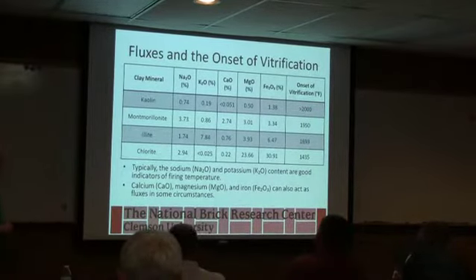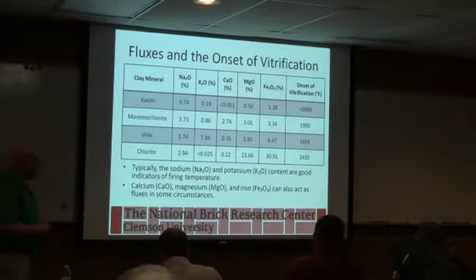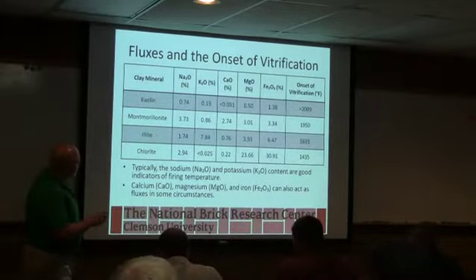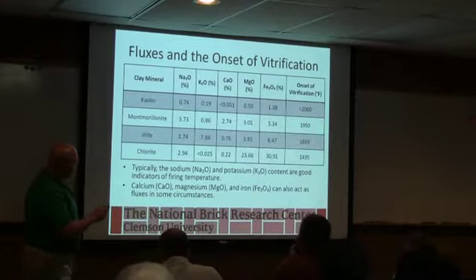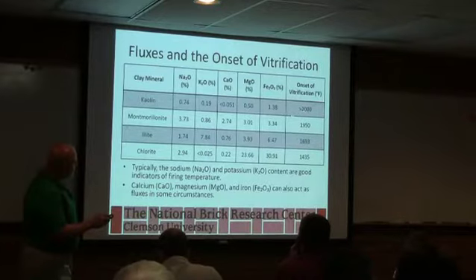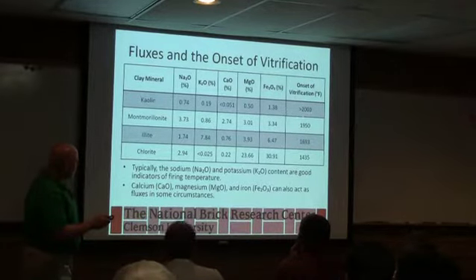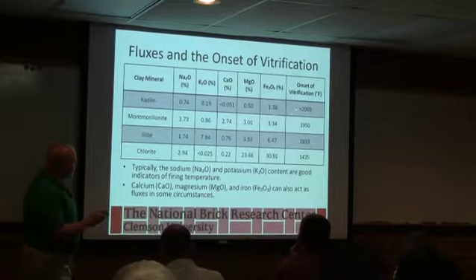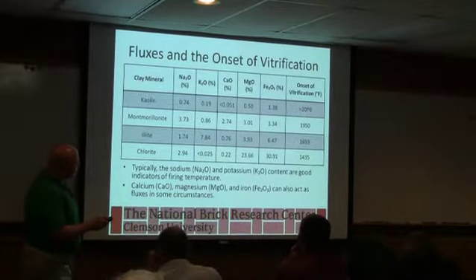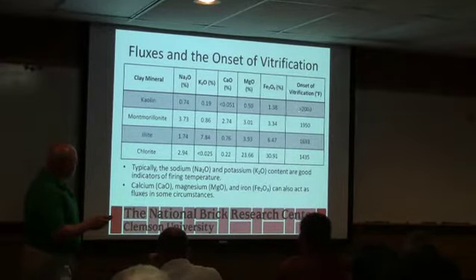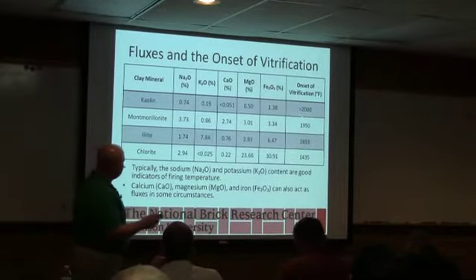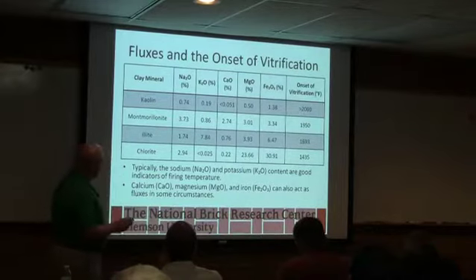So, just an idea of onset of vitrification and the different amount of fluxes. If we look at these materials, I use something called a dilatometer to look for the onset of shrinkage in these, or where they start to form glass. I said greater than 2,000, but it's probably a lot more than that. I was being generous here when I made this chart. This wasn't the purest kaolin. A very pure kaolin, you'd get up to a very high temperature before you see any meaningful vitrification.